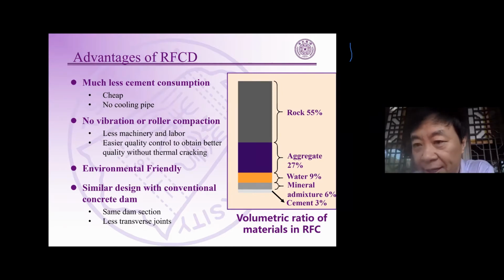of aggregate. The aggregate in self-compacting concrete is usually with a maximum grain size of 20 millimeters. And of course, we have about 9% water, and we usually have mineral admixture such as fly ash or stone powder, about 6%, and only 3% cement. So in rock-filled concrete, we use very little cement, and we get much less cement consumption. This makes rock-filled concrete cheap, and without cooling pipe, it is very easy to construct.